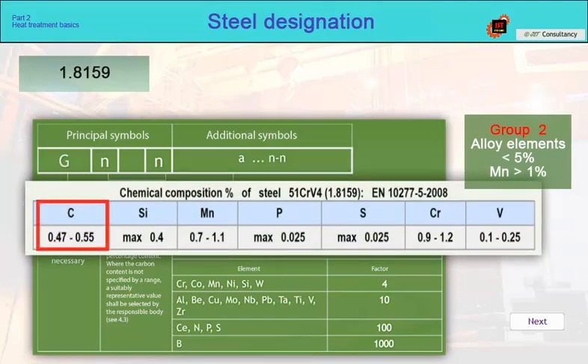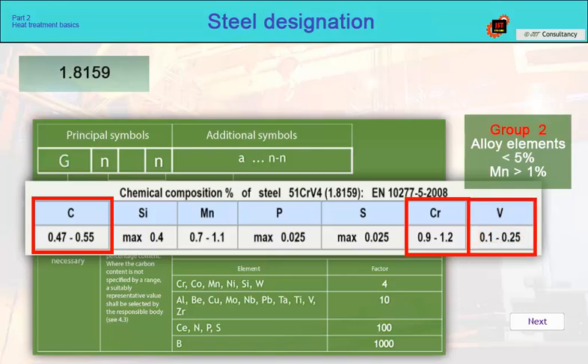1.8159. Its chemical composition is as follows. The steel has a carbon content of 0.51%, 1.1% chromium, and 0.17% vanadium. Its EN designation will be 100 times the carbon, which is 51. Then the alloying elements chromium and vanadium will be listed, and 4 times the chromium content. 4 times 1.1 equals 4.4. This number is rounded down to the digit 4. Vanadium will not be listed numerically, since its 4 times amount is less than 1%. The steel will therefore be designated 51 chromium vanadium 4.